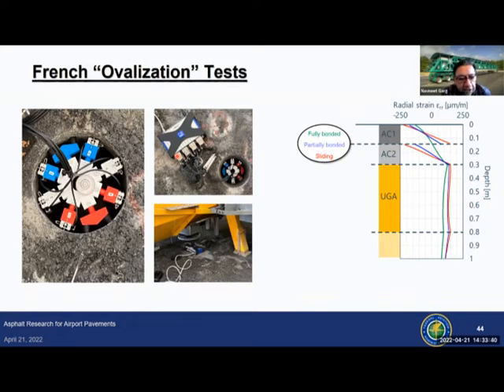So it's a displacement-based strain transducers that are used in this particular device. And by the way, this device is printed using a 3D printer. So you take a core out of your pavement structure, position this device just above the interface, measure responses, and the strains are measured in three directions. So you have one direction, then perpendicular to that, basically the three principal axes, and you get your strain responses.